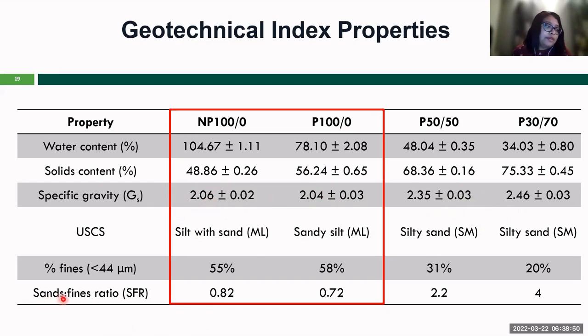Other important findings here concern the non-polymer and polymer. If you look at the index properties, it's almost a similar kind of behavior. And if you look at the sand to fine ratio, the 100% material was higher than for fluid fine tailings. Looking at this ratio, both for non-polymer and polymer, it is higher than the FFT from the literature, which shows 0.1. So this value was higher compared to the fluid fine tailings.